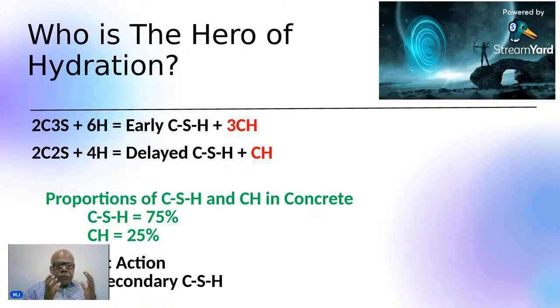So, if you note very carefully, the first equation, tricalcium silicate, gives you very high strength, but along with that, it is giving you 3 molecules of calcium hydroxide. And the second equation, dicalcium silicate, gives you only 1 molecule of calcium hydroxide. So a slightly slow setting of your cement, the delayed CSH gel, actually gives you durability of the concrete because it is creating less of this side effect called calcium hydroxide. We will look at calcium hydroxide in more detail and see the amount of issue that it creates in our concrete.